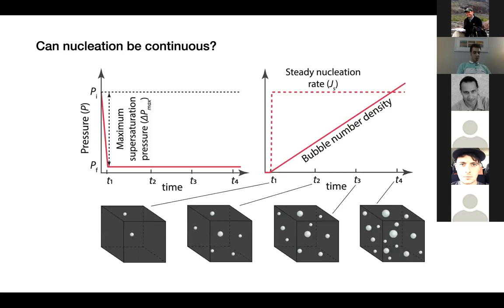So to test whether nucleation can be continuous, we did some more experiments similar to the previous experiments with one main difference. Experiments were divided into several groups. In each group, samples were hydrated at the same saturation pressure. They were decompressed with a similar decompression magnitude and rate. They were held at the final pressure, but they were quenched at different times to see whether bubble number density changes through time.